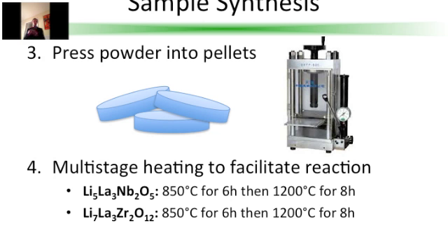So then, after mixing the reagents, I would take the mixed reagents, press them into a pellet with a machine press, and then heat that pellet at temperatures ranging from 850 degrees Celsius to 1200 degrees Celsius to actually facilitate the reaction. And for both lithium lanthanum niobate and lithium lanthanum zirconate, I have to heat the samples at 850 degrees Celsius for 6 hours and then at 1200 degrees Celsius for 8 hours.